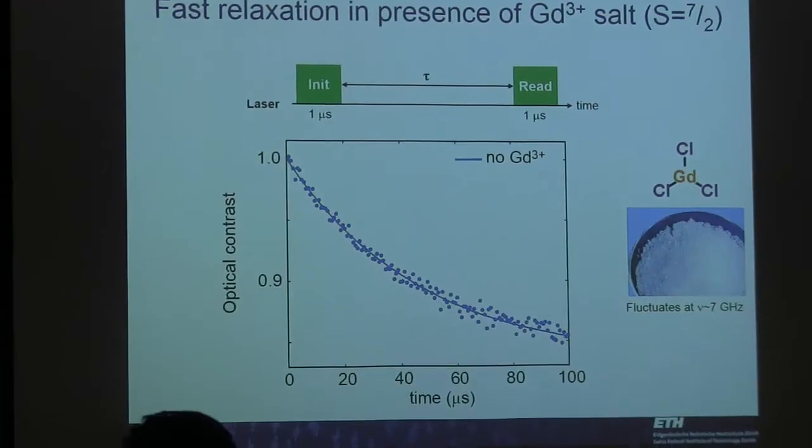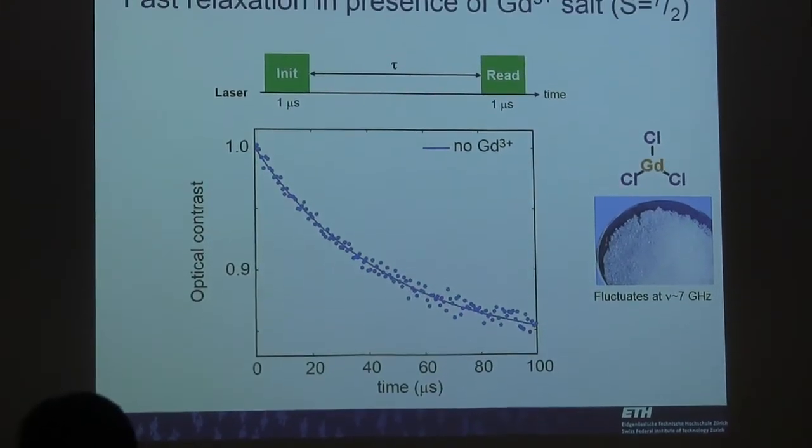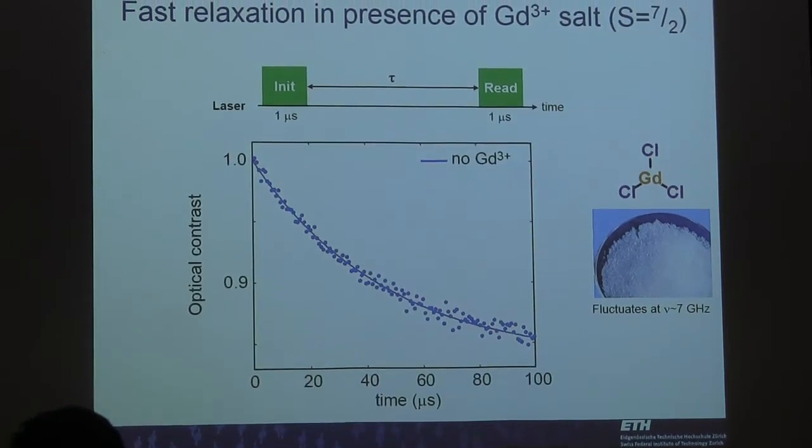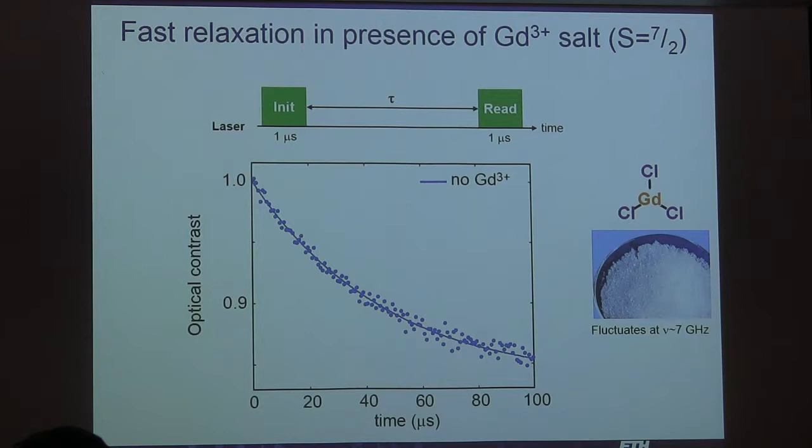Okay, there is a third example for this, relaxometry. So here is a relaxation curve of this NV center. Again, we prepare in 0, we do nothing with microwaves. We wait for some time tau, and then we read out whether we are still in 0 or in 1. And this is for a nanodiamond here, which has very short T1s because it has many impurities. So the T1 time, the decay time, is only about 40 microseconds.